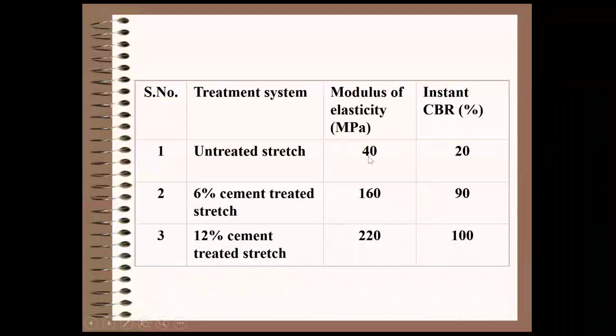Then modulus of elasticity without stabilization was only 40 MPa, and when cement stabilized, it significantly increased. This also indicates that yes, the material has become very stiff. It is not simply bearing capacity; stiffness matters in road construction. That is what happened here.